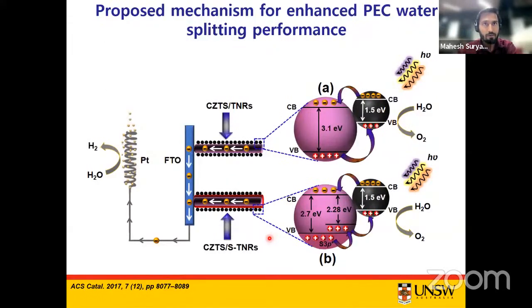Now, to gain further insight into the electron-hole transport mechanism, or charge separation behavior, in the CZTS-sensitized sulfur-doped TiO2 nanorod arrays and only CZTS-sensitized TiO2 nanorod arrays, we have drawn these schematics, which clearly explain this mechanism. We all know that a suitable semiconductor heterojunction with a type 2 band alignment is highly beneficial for efficient charge separation in a typically n-type photoelectrode, since it suppresses the electron-hole pair recombination and improves the transport of these photoexcited charge carriers.